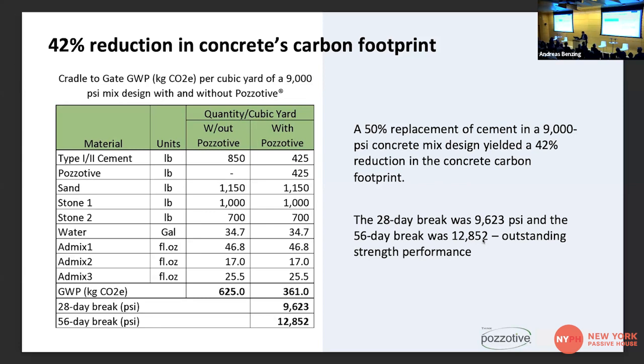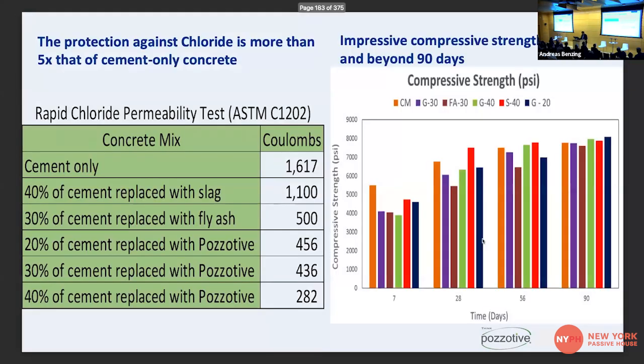Well, if you think about it, this was a 50% replacement of the cement in this 9,000 PSI mix design that was used at Hallett's Point. You can see we made strength. It creates additional compressive strength because of the calcium silicate hydrate reaction and the calcium hydroxide bonding with the silica. In the end, we create higher strength. We reached our goal at 9,600 PSI for a 9,000 PSI mix, and at 56 days, we're approaching 13,000 PSI. So an amazing benefit. You're increasing compressive strength, and there's even a bigger benefit. This is an interesting study that was done by City College of New York School of Engineering.